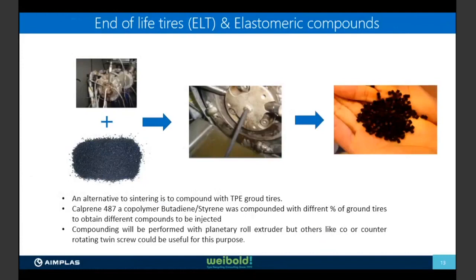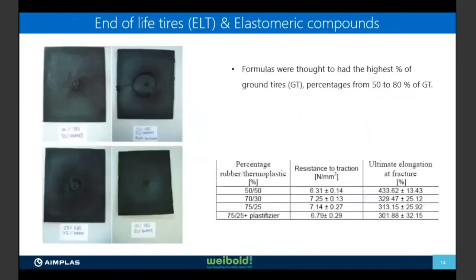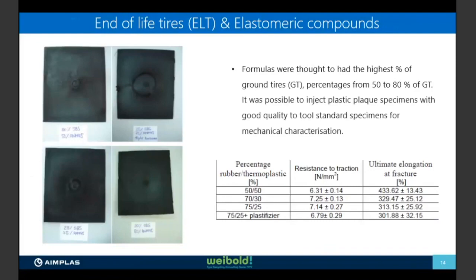So compounding was performed with a planetary roller extruder, but other extruders could be applied for this purpose. I think that in that case, because of the melt flow index, it was quite interesting to obtain those compounds. And what we worked on is formulas where we try to reach the highest percentage of ground rubber. So we reached percentages up to 75-80%. Here on the left, you can see the appearance, and the appearance was quite good. And afterwards, we injected the soles of the shoes, and the company was quite happy with that, which is not so usual, because sometimes when you are doing research, it's not that easy. And we obtained different values in mechanical properties that were okay, and met the requirements of the customer. This is another approach, okay.